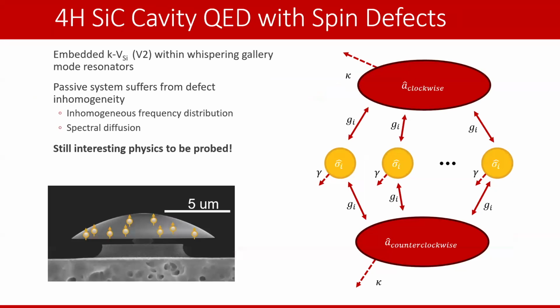So that means with whispering gallery modes and the silicon vacancy center, our cavity QED system looks a little bit more like this. Because the whispering gallery mode has two, for the most part, degenerate photonic modes, clockwise and counterclockwise modes, we now have this additional photon mode here. But this whole thing is passive. The defects have been implanted with electron beam radiation. There are moving charges in the silicon carbide, like I mentioned before. You saw that the spectral lines don't sit still. So these defects move around in frequency. And so there is interesting physics to be probed when your defects are moving around with this spectral diffusion.